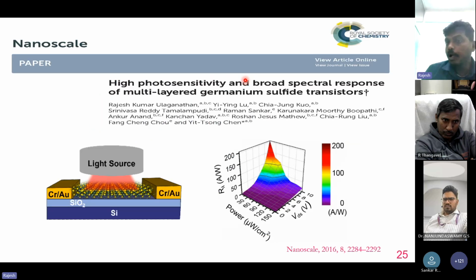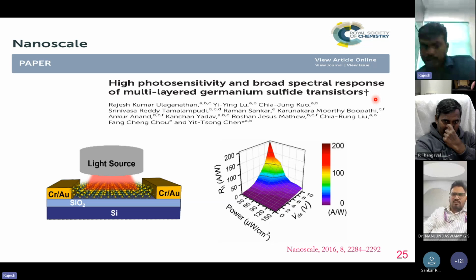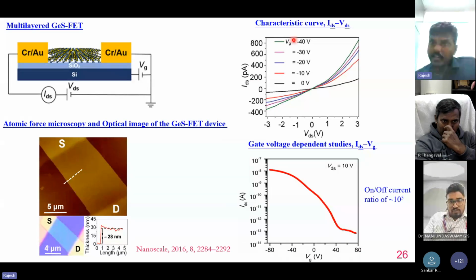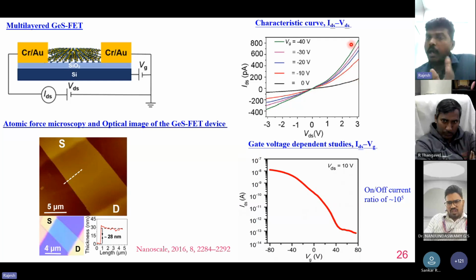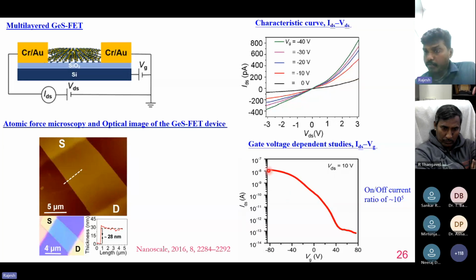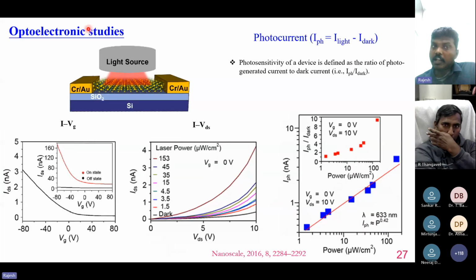And also we grew a p-type material called germanium sulfide. Here we can clearly see that when we increase the negative gate voltage, we observe an increase in the current, which shows this material is p-type. Then we showed it has a high on-off ratio, almost 10 to the power 5, which is quite good in the 2D family. And again, we shined light on our germanium sulfide and try to extract the photoresponsivity of our material.